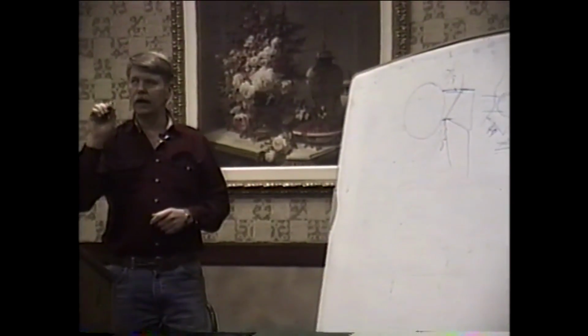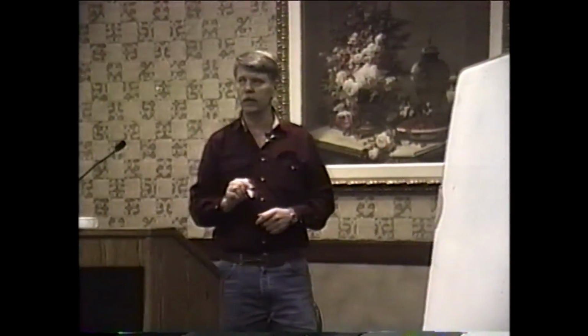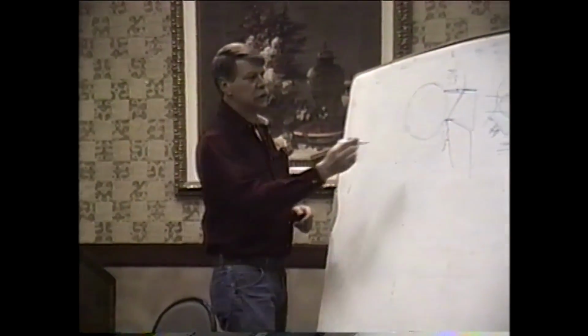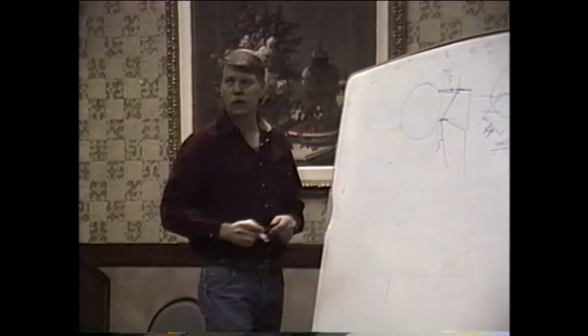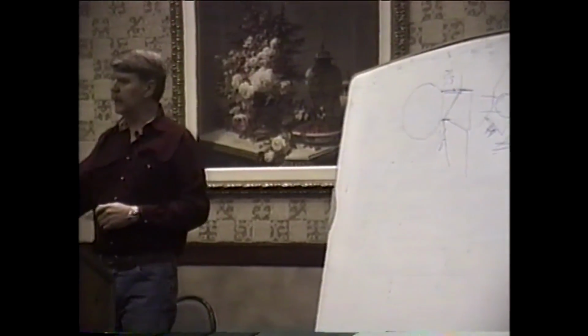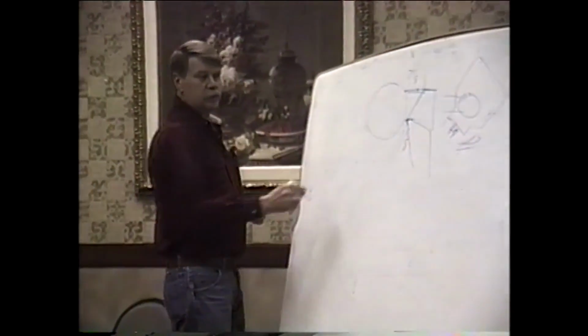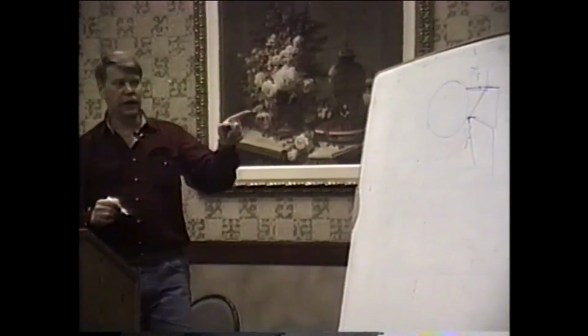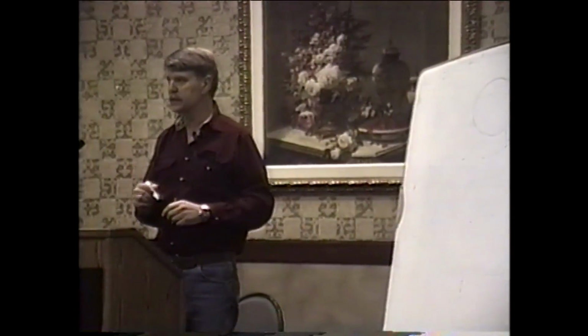The primary important first thing to remember is the first pass. That one right there, right through the corner. I set them up to where they've actually got about 25 to 30 thousandths gap between the two. I never let them touch. And when I go through there with the first pass, it's going to be hot and fast, but it's going to go all the way through. I want weld metal hanging out the bottom. Once you get that, then the rest of it is just fill-in work, and there's a bunch of it.